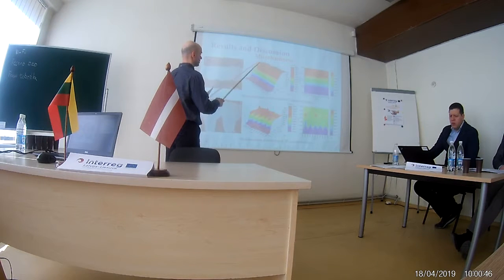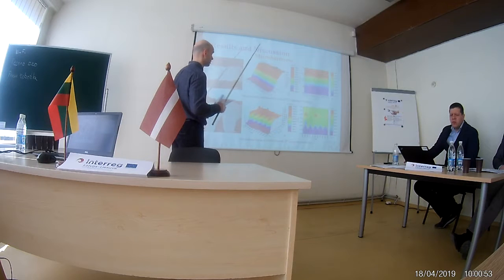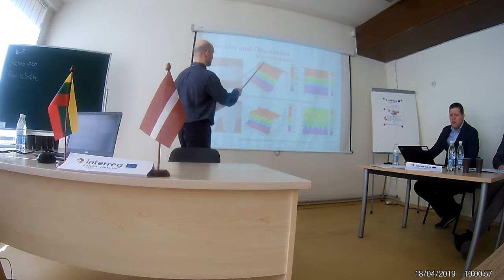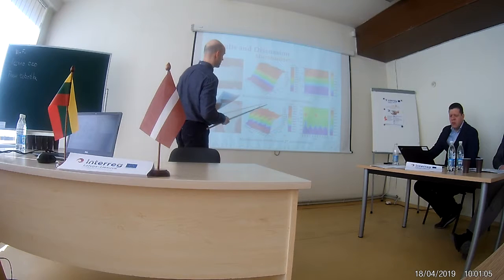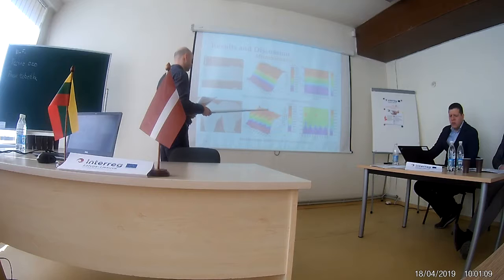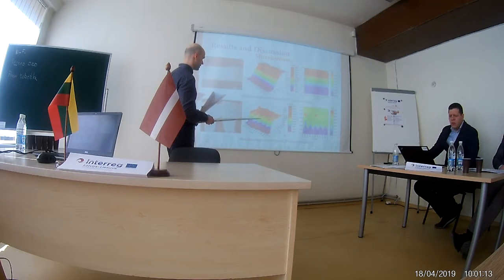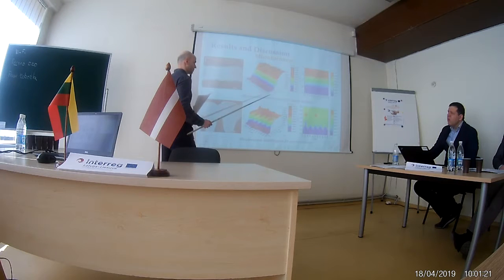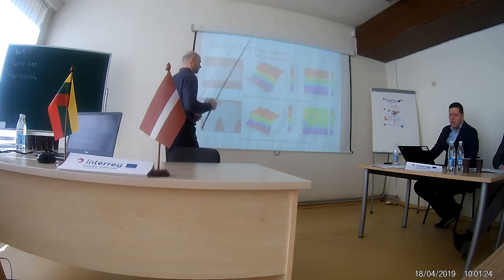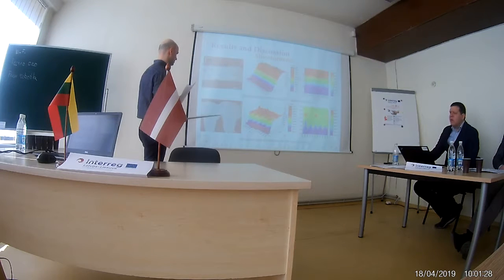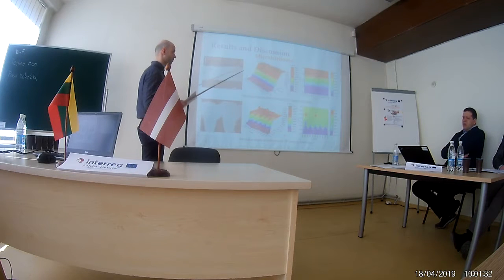As it is seen, the first coating demonstrates a fairly uniform distribution along the overlap direction and direction of cladding, the x-axis. However, an abrupt transition of properties along the depth, the y-axis, is evident. In its turn, the second group coating displays heterogeneity of properties along the x and y-axes. This applies to areas of increased microhardness, which apparently correspond to the cavities between contiguous keyholes. Obviously, to exclude these unfavorable peaks, the smallest value of overlap ratio should be used.